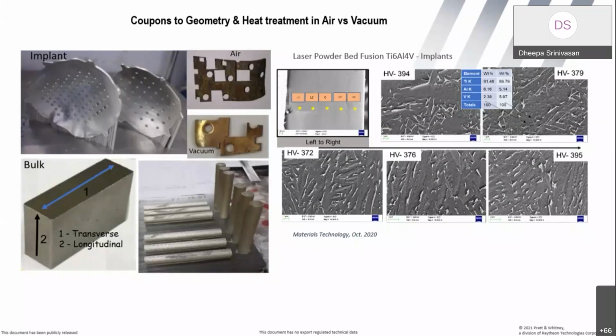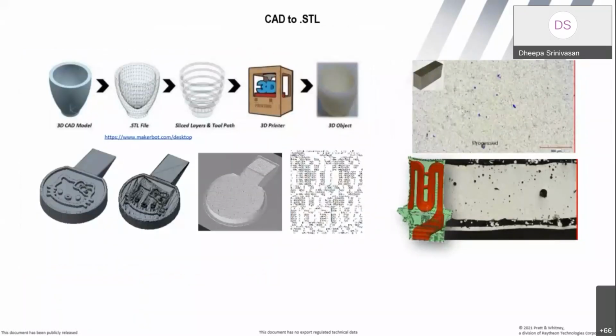Okay, so I come now to the 9th challenge. And what is this challenge? This is again something we have faced several times. When I take a bulk coupon and estimate the porosity and the mechanical properties, here you can see the same 1 inch by half an inch by half an inch coupon. And if we cut it up, the porosity values are hardly anything on the top right-hand side picture, less than 1% definitely.